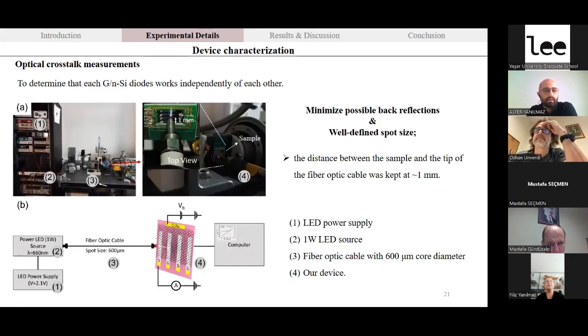The most important thing for detector arrays on a single substrate is the optical crosstalk measurement. This is done to determine that each graphene n-type silicon diode works independently of the others. Here you can see the detectors, with light striking on the junction. We kept the distance the same to minimize possible back reflections, and for a well-defined spot size we used a fiber optic cable at a 1 millimeter distance. Then we did this experiment for each detector in the array and collected data from them.